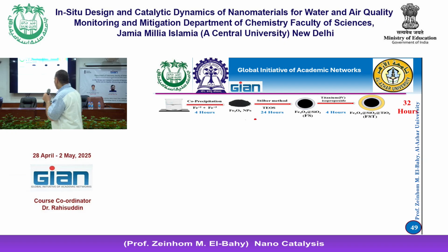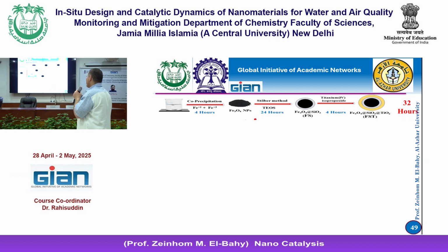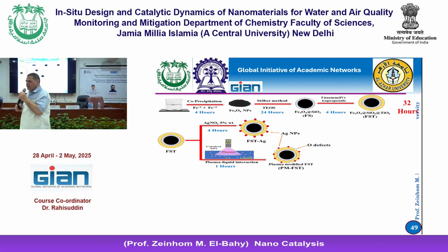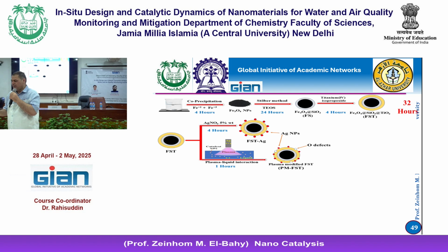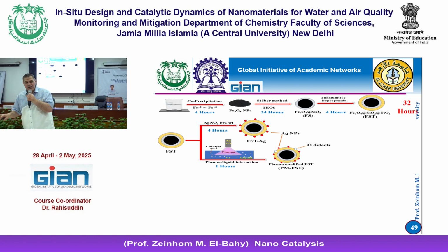We prepared magnetite by mixing both ferrous and ferric for some time, making co-precipitation, and we obtained magnetite as nanoparticles like this. And we added TEOS as a source of silica to make a shell of silica. Then again, we added a titania source to give a titania shell. This means we have, how many shells? We have 2 shells, okay? And we make decoration with silver. We can make decoration with silver for this material by plasma, or conventionally by adding silver and reducing it over these materials.